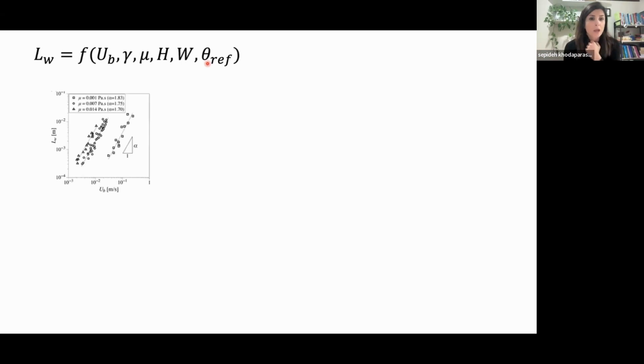So we knew that this length should be a function of at least the capillary number, which is the viscosity multiplied by the bubble velocity over the interfacial tension between the two phases. In all of these scenarios that I was discussing, there's always an air bubble in water, or water mixed with another liquid, just to tune the surface tension or the viscosity. There is the geometrical feature: H represents the height of the channel, W is the width of the channel, and theta is some sort of contact angle representing the wetting in the channel. The smaller the theta, the more wetting the channel is, and the larger, the less wetting.